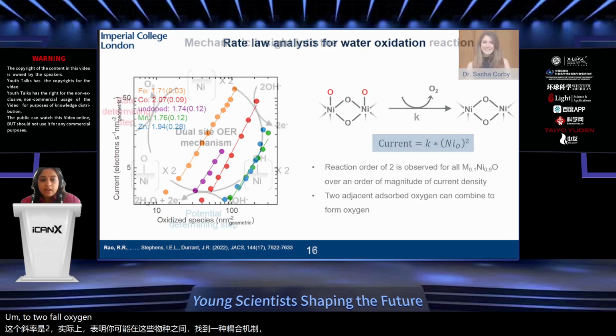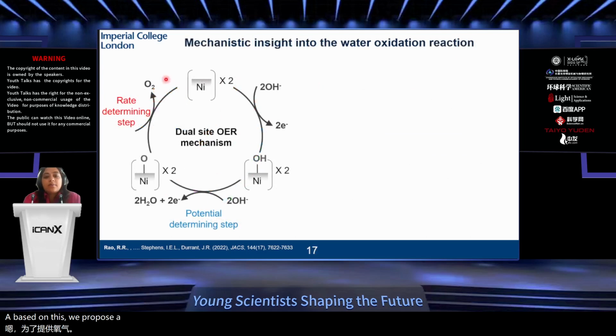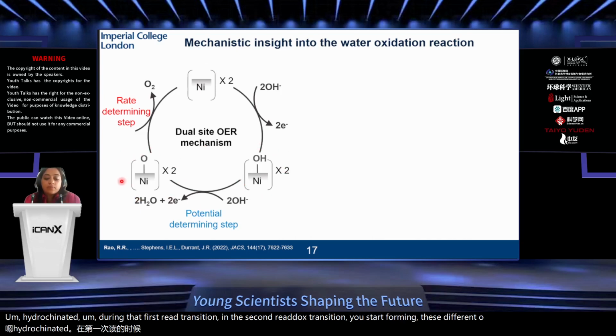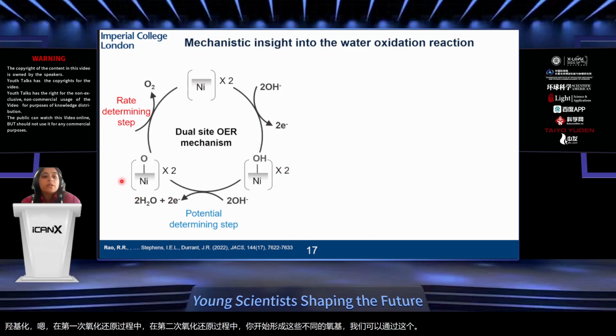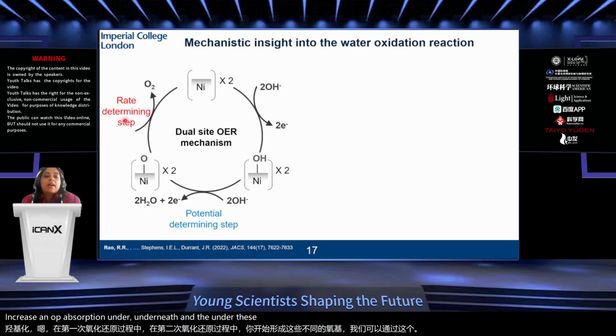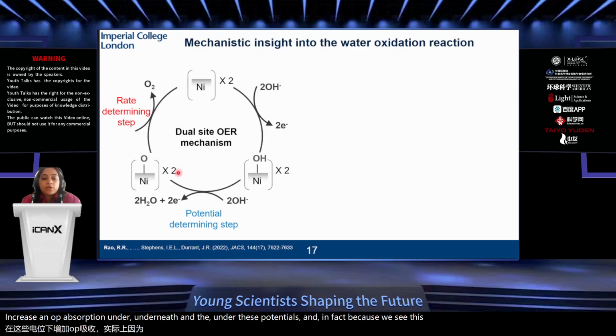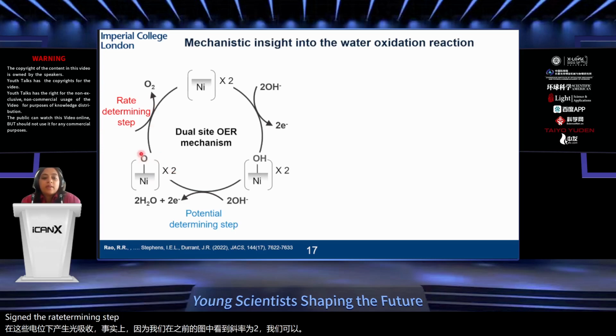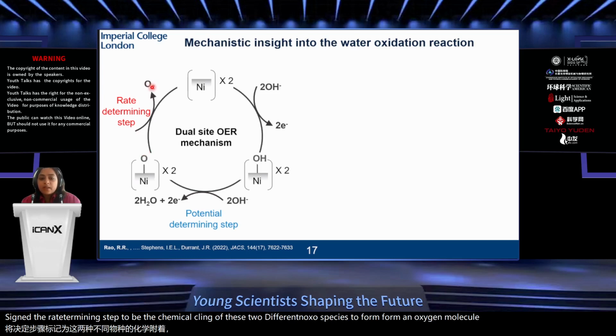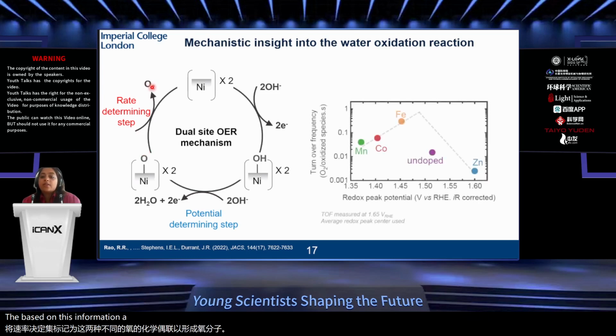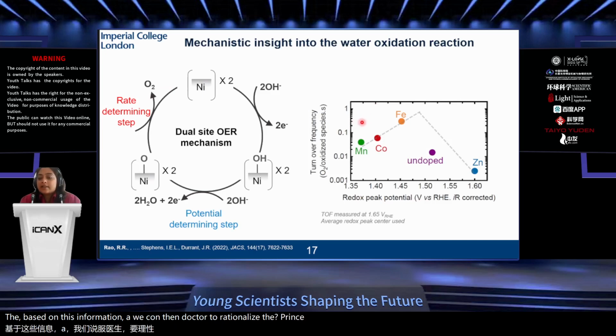Based on this, we propose a reaction pathway where you have these nickel centers that get hydroxylated during that first redox transition. In the second redox transition, you start forming these different oxo groups, and we can see that by the increase in optical absorption under these potentials. And because we see this slope of 2 in the previous graph, we can assign the rate determining step to be the chemical coupling of these 2 different oxo species to form an oxygen molecule.